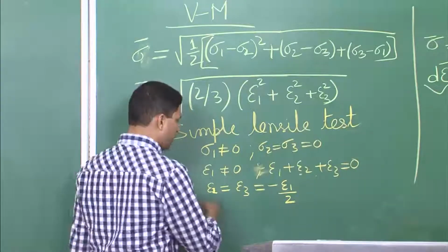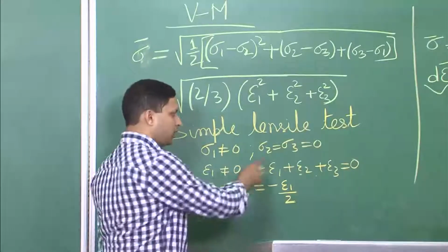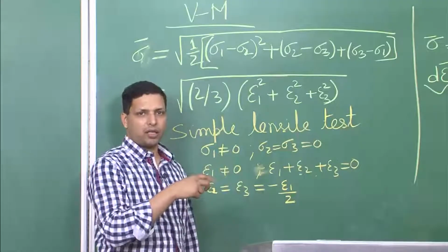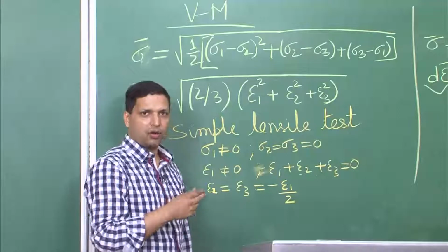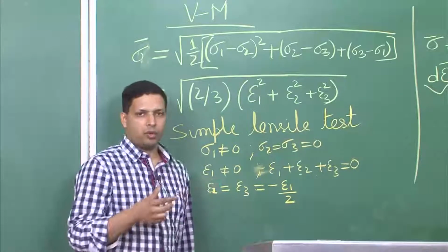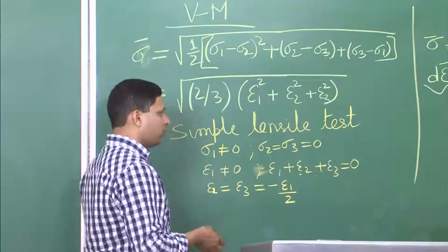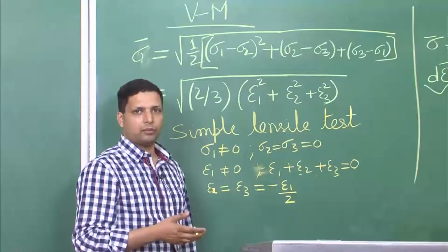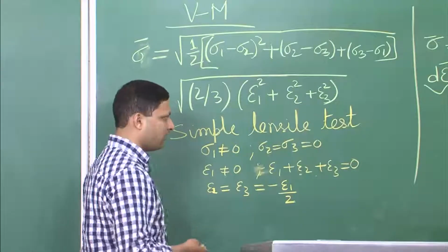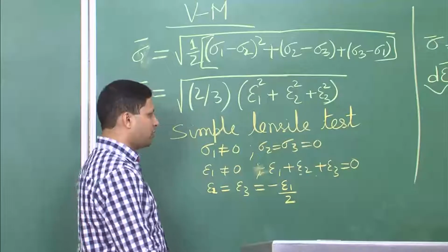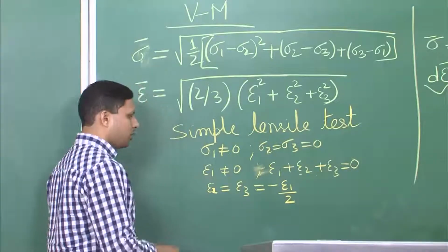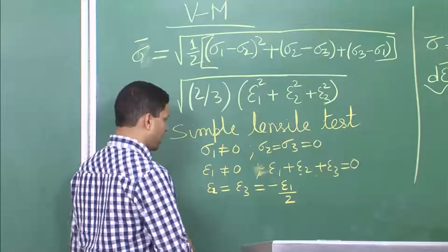If you keep elongating the material without it contracting on the sides, it would mean that the total volume is increasing, which is what we have forbidden. We had taken an assumption, and that is a valid assumption, that volume does not change during plastic deformation, in the range we are interested in.